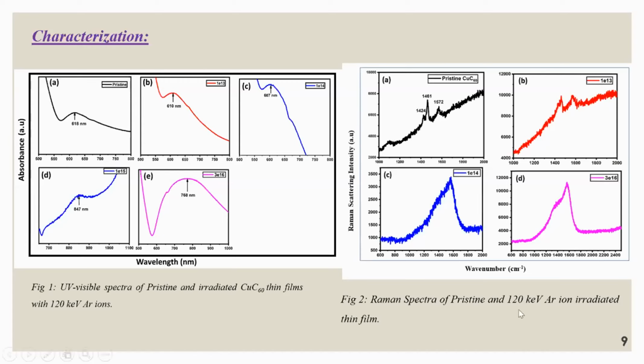This is the Raman spectra of pristine and 120 keV Ar ion irradiated thin films. We can observe the dominant peak of C60 fullerene in the pristine sample, and after ion irradiation, it is converted to amorphous carbon. So the C60 fullerene is converted into amorphous carbon. That is why the refractive index has changed and the blue shift has occurred.